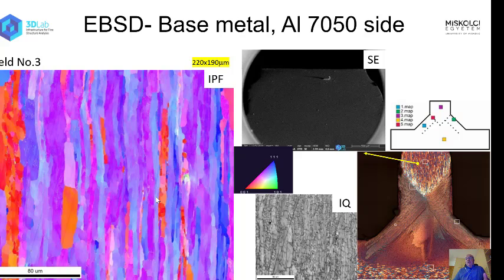And now I come to the most fascinating pictures, the electron backscattered diffraction from this particular structure, which happens at a much smaller scale. Most of you know that this analysis requires hours of scanning and collecting the diffraction pattern from the grains, sometimes a day. You can see that the grain orientation is clearly revealed in the EBSD picture, as opposed to the Barker's, which was very uniform. EBSD shows some orientation. No big deal. This is what you would expect from a rolled material.